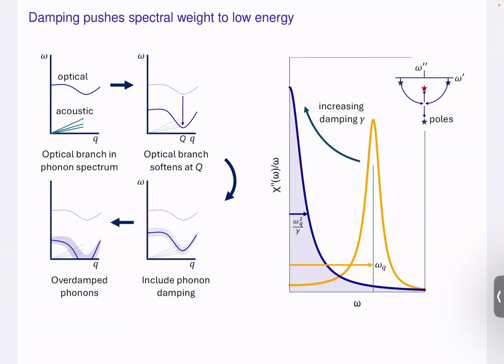It has poles, zeros in the denominator, in the complex omega plane, with an imaginary part and a real part, and normally they sit near the real axis. But if you increase the damping, then the poles move towards the imaginary axis. They eventually hit the imaginary axis. That's when they are critically damped. And then if you increase the damping further, one pole moves off to minus imaginary infinity. So that's very rapid decay. The other one moves off towards 0.